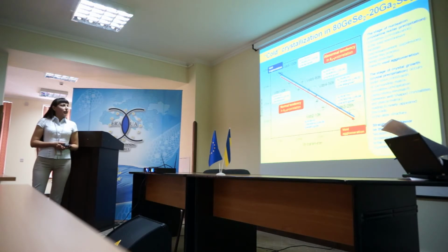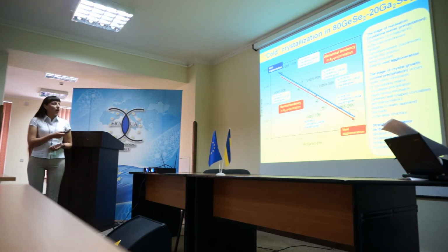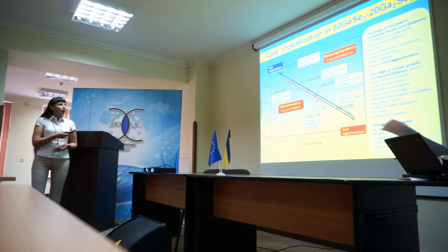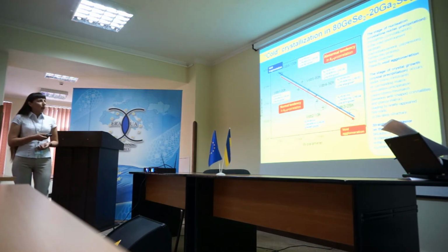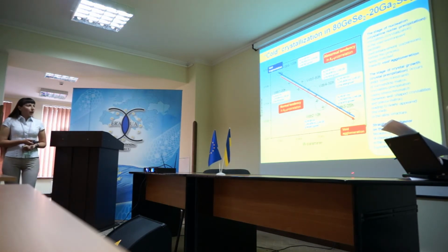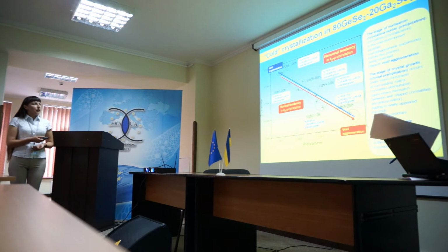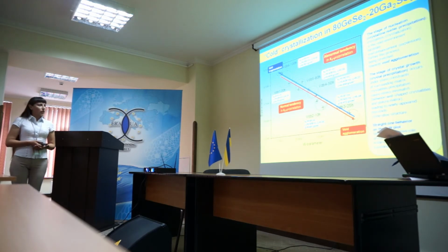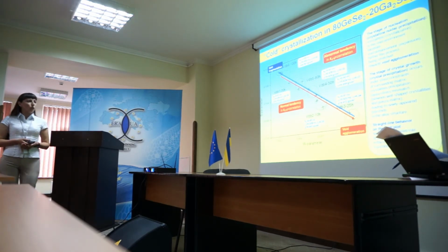At a normal tendency, we have an increase of the lifetime of the second component and a decrease of the intensity of the second component. In this case, density is decreased also. This tendency is correlated with positron annihilation lifetime data and reflects void agglomeration in this case.